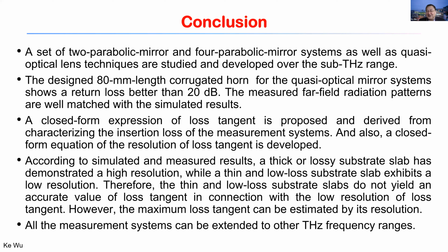We also designed a very high quality Gaussian beam launching system based on a corrugated horn. And of course, in this work we developed a very accurate loss tangent prediction theory based on the loss tangent resolution formula. This gave us certain assurance regarding the measurements for low loss materials.